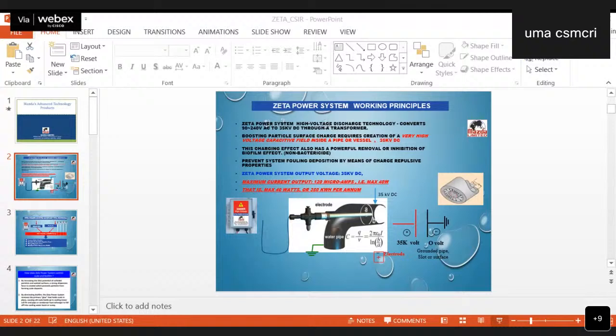Yeah. So this zeta now has a wonderful application for RO, reverse osmosis, because reverse osmosis has a tendency to get clogged with the scaling that comes. Normally the water with high TDS enters the RO, and every 15 days or a month, or maybe once in 45 days, depending upon the TDS, the RO has to be opened and cleaned, because the scales stick to the film or membrane of the RO. But if you incorporate a zeta, it does not allow scale formation to take place on the RO membrane, because of which the throughput of the RO increases and the life of the membrane also increases to a very great extent.